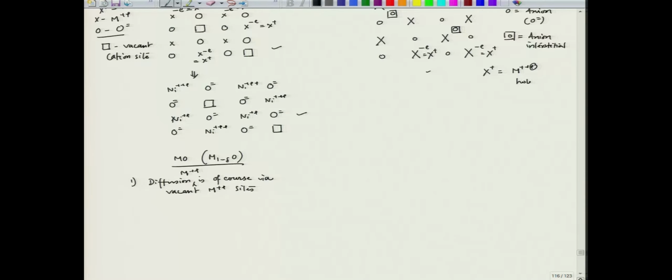Second, this reaction, which is the anodic reaction, would happen on the metal metal oxide interface. Third is the metal oxide, and of course the other corresponding reaction, O plus 2 E equal to O 2 minus, would happen on the oxide metal oxide interface.